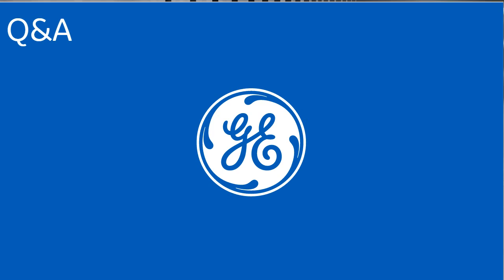Great, thank you. A couple of questions on this, so I'll ask just one. What is the effect of the electron beam on the microstructure of the part? This is probably a good question for Isaac. Yeah. So as such, I wouldn't say that the energy source itself really affects the microstructure, but one of the benefits that I see with EBM is that we can, to some extent, control the solidification rate depending on how we choose to melt. And we can also control the solidification direction. And those are key in order to have this kind of tailored microstructure. So by controlling the solidification direction and the solidification rate.